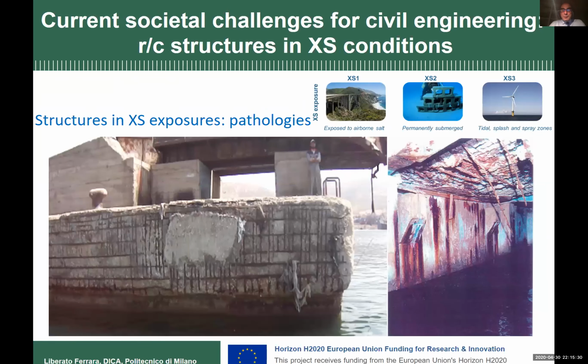These are structures which are really not older than 10 to 15 years, so which were built, designed and built according to the prescriptions. On the left is a harbor dock in Morocco, and on the right is a structure in a harbor in the Mediterranean coast of Spain. And you can see very damaged spots, which probably occurred, in the case of the harbor, due to repeated hitting by the ships, by the vessels. But also because one thing is what we design, another thing is what we construct on the site. There are several variables intervening between them.